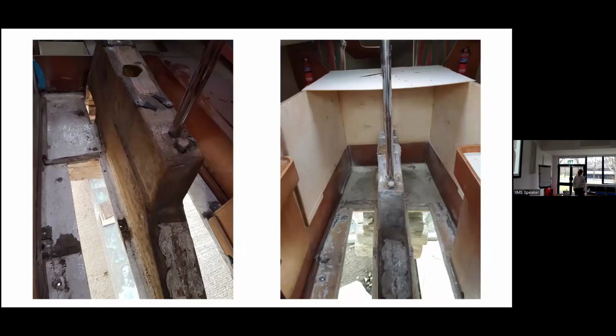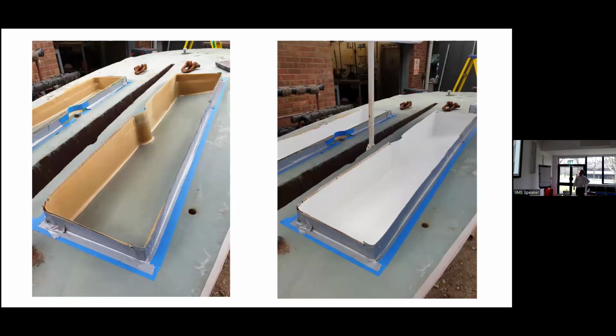Next slide. You see inside. This is part of the reason that the work stopped on it when the keel was originally taken off. The boatyard could not get the keel off, so they started chopping the interior. So I reinstated a lot of the interior laminate around the keel area. Next slide. And I remoulded these rebates in the keel in chop strand mat, and they are posted into those cutouts in the bottom of the hull. If anybody knows this design, it's quite a unique 30-year-old French-built boat.